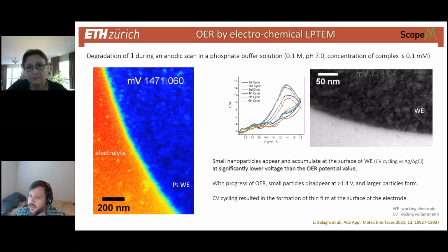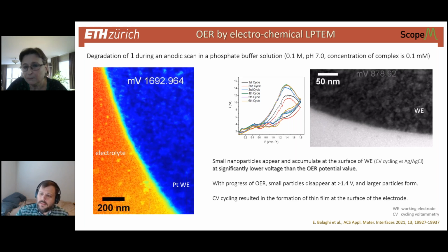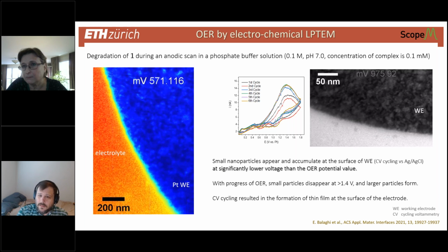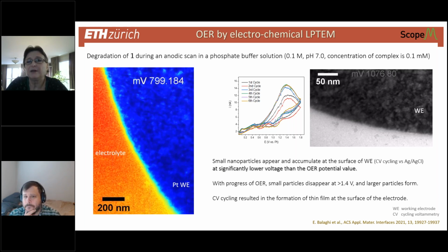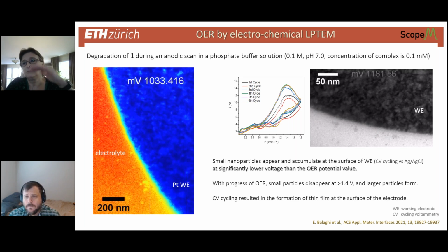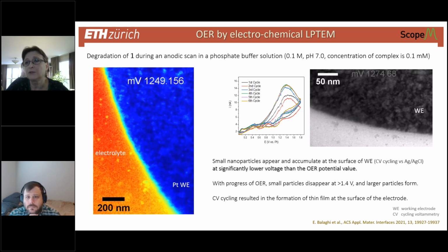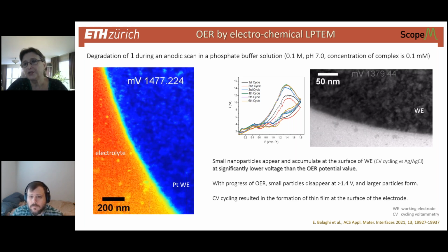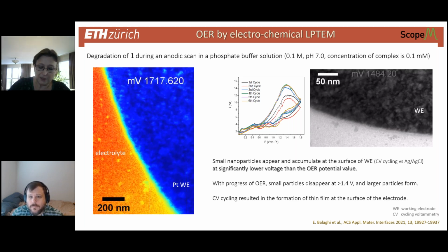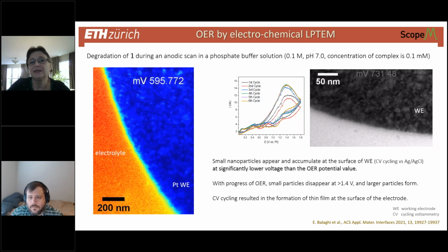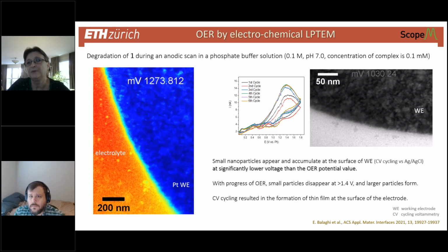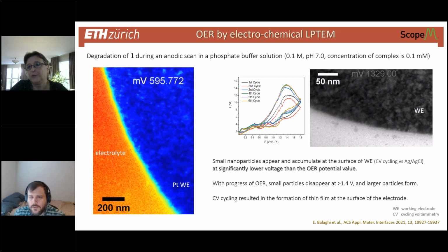Next question we have. They would like to know exactly what went wrong with the STEM EELS in analyzing the copper oxide phase. There was not enough signal to see. It was very, very noisy. You basically have a beaker of water, and you shoot through it, and a small volume fraction of copper or whatever copper species evolve. You have to illuminate for a long exposure for the EELS spectrum to give a decent feature. We tried a few times, for 10 minutes or 15 minutes. You irradiate the area, and you hardly see anything. Just too thick, too huge a volume to reach the spectrometer.